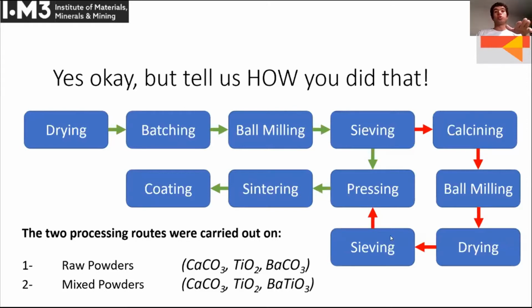So we undertook both those two routes for two mixtures of powders, raw powders, and that's how we obtain them in nature: calcium carbonate, titanium oxide, barium carbonate, and mixed powders, just adding calcium and titanium to preformed barium titanate.